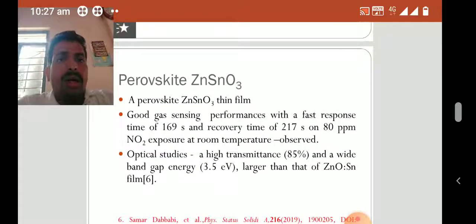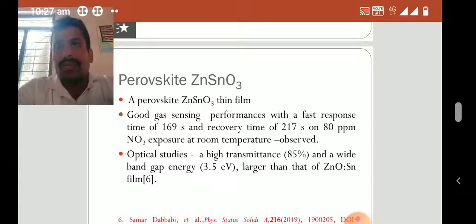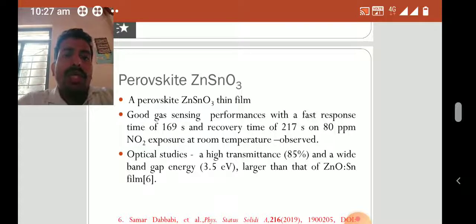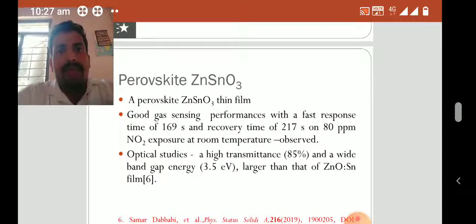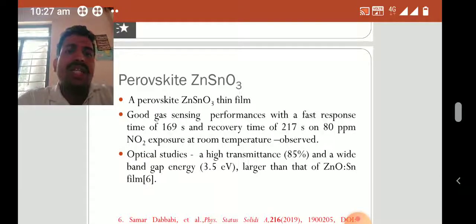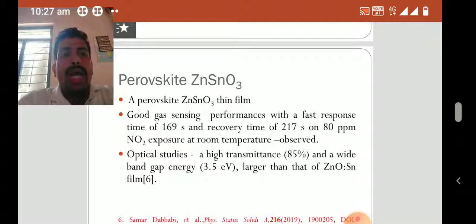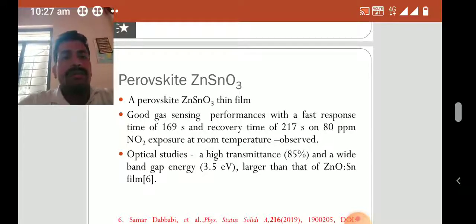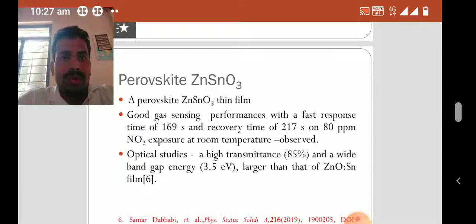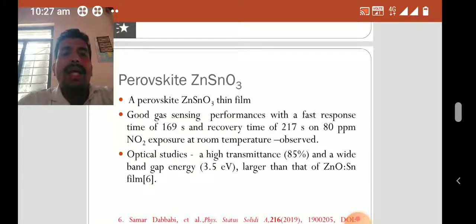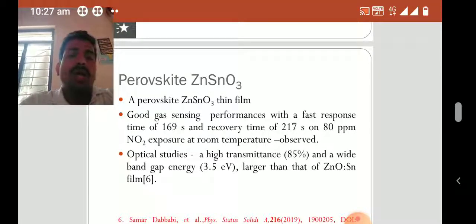Let us consider perovskite zinc stannate. What was the research conducted? A perovskite zinc stannate thin film was prepared. Good sensing performance, with a response time of 169 seconds and recovery time of 217 seconds on 80 ppm nitrogen dioxide exposure at room temperature, was observed. Here, optical studies were carried out: a higher transmittance of 85%, and a wide band gap energy of 3.5 electron volt, which is larger than that of zinc oxide tin oxide film.